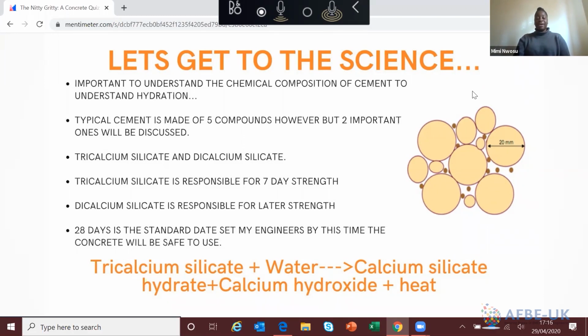So most people hear in the engineering world that with concrete, the first 7 days of the curing process is the most important. The fastest part of the reaction is. And tricalcium silicate is responsible for 7th day strength. Dicalcium silicate is responsible for the later strength. So what happens? So tricalcium silicate in the cement, when it reacts with water, produces hydrates and hydroxides and also releases some sort of energy. So when the hydrates and the hydroxides are produced, they form chemical bonds, therefore compacting the concrete much more, therefore giving it strength. Now, that's in the first 7 days.